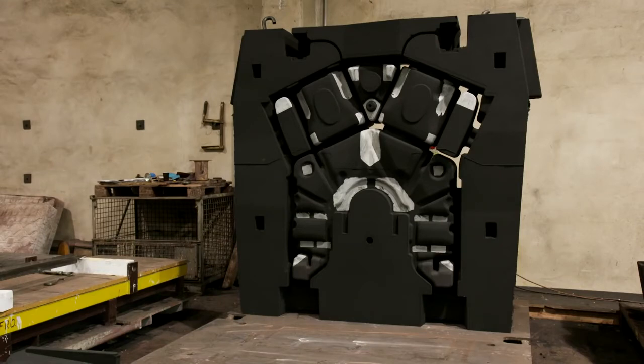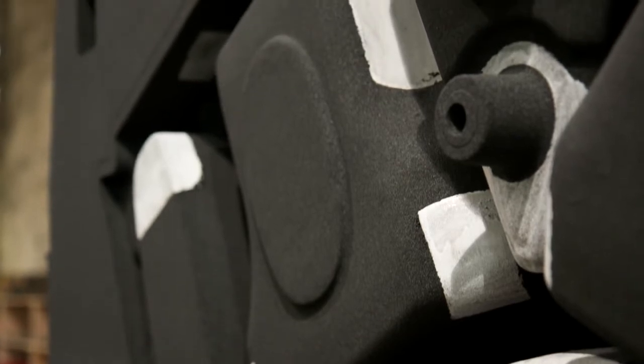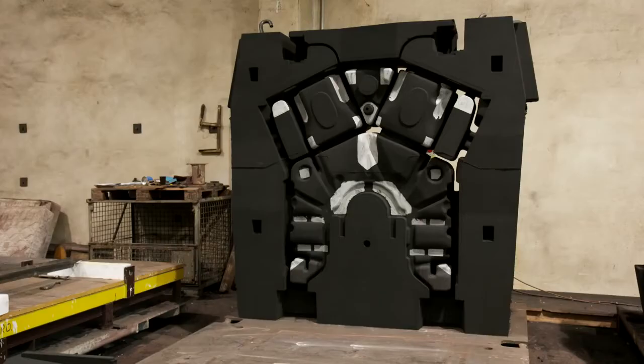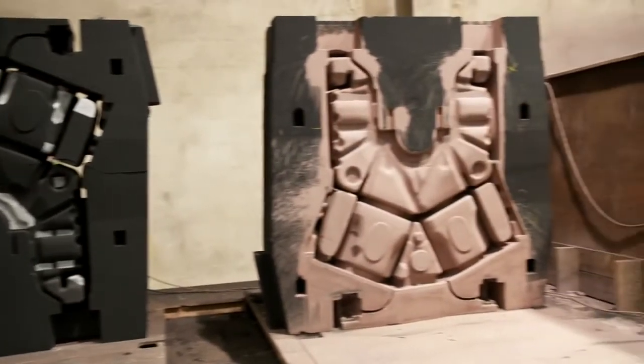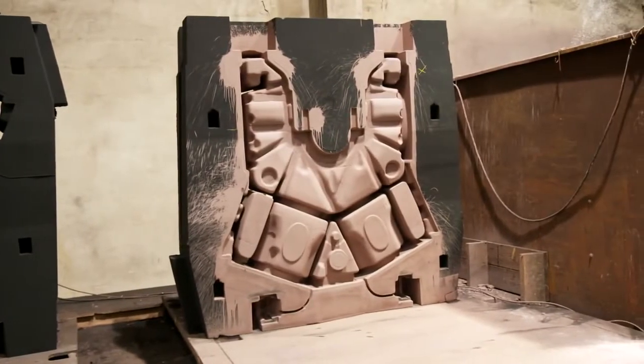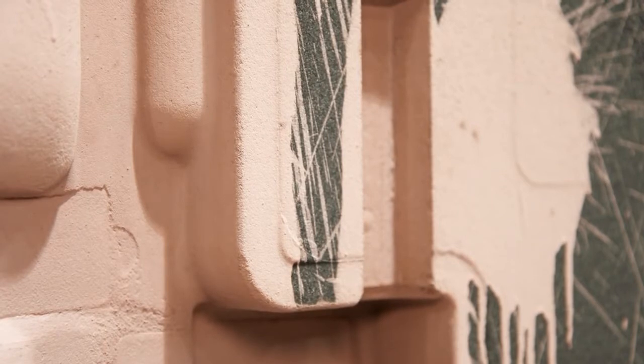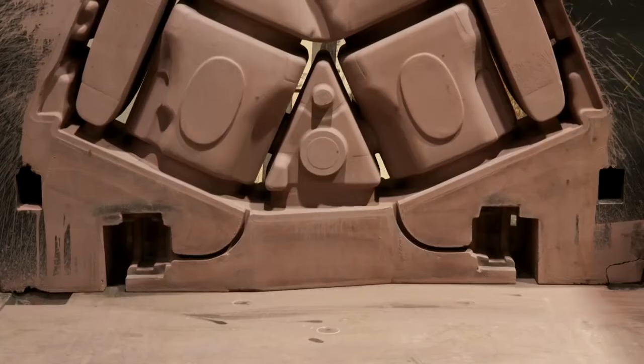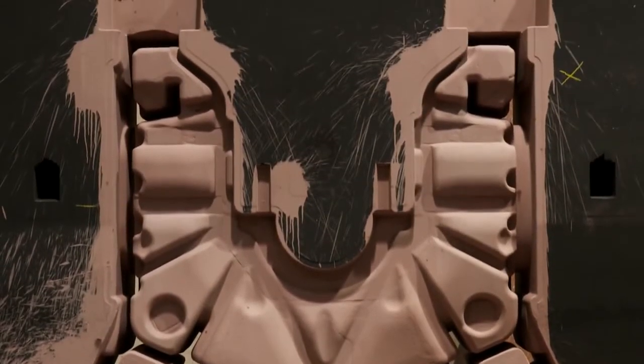This is what the various parts of a crankcase mold look like. These two disc cores consist of resin-soaked quartz sand, which, after setting, has become rock hard. 10 of these cores in sequence comprise the mold of a Series 8000 crankcase. Prior to casting, each template is given a coating which has a horrific smell to it. The coating prevents the sand from mixing with the steel during casting.